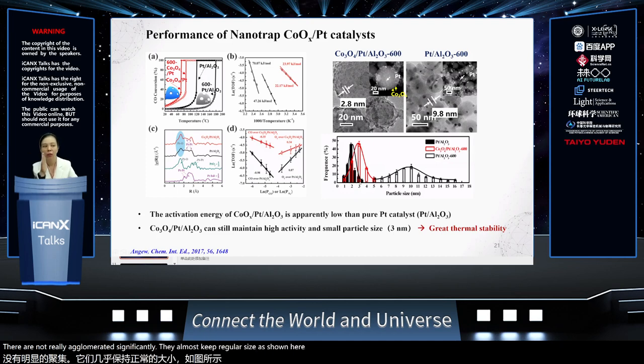You just see a little bit of a shift in the red curve, a slight shift to the right. What if you do not do this kind of coating or anchoring structure? The particles will go completely to a much larger size, as shown here, with the sizes listed here.